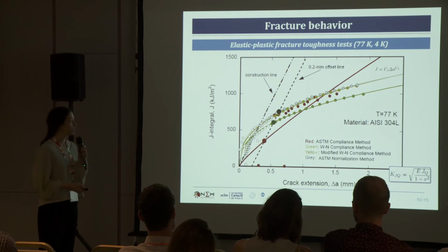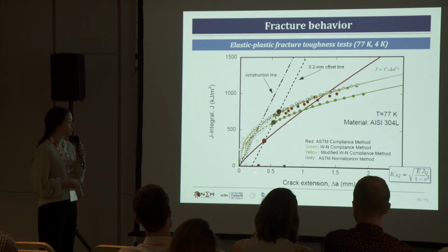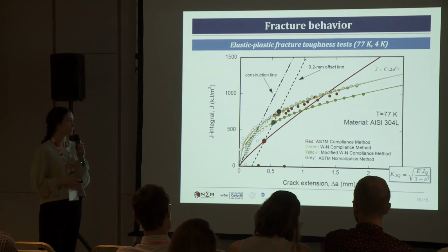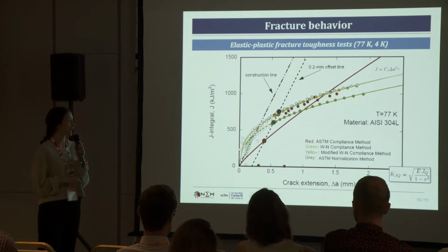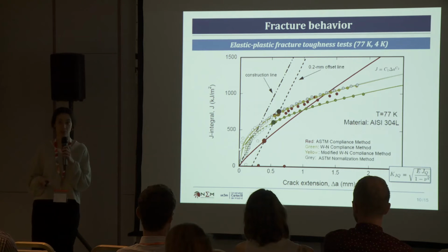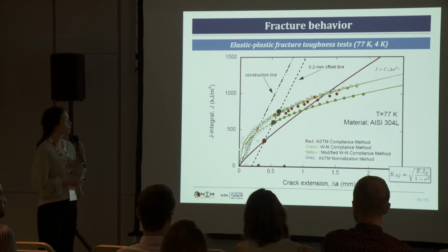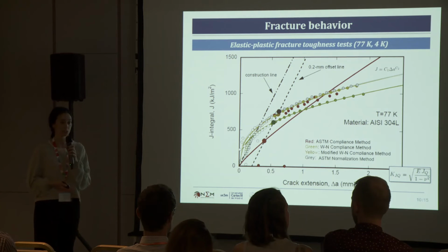This is the conclusion. Then, if we move to the Weiss-Nylas compliance method in green, we have it here. Now we have corrected the problem of the negative crack extension. We don't have it. And as we have corrected also, the crack size is quite soft. Then we have the yellow, that is the modified version. The difference is just that it lies above. Why? Because we have recalculated the J value. This is the difference. And then if we compare it with the normalization method, you can see that the gray and the yellow are quite similar, okay? So our conclusion, better to use the normalization method.